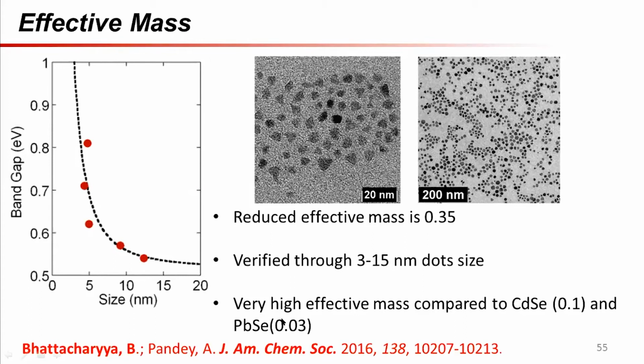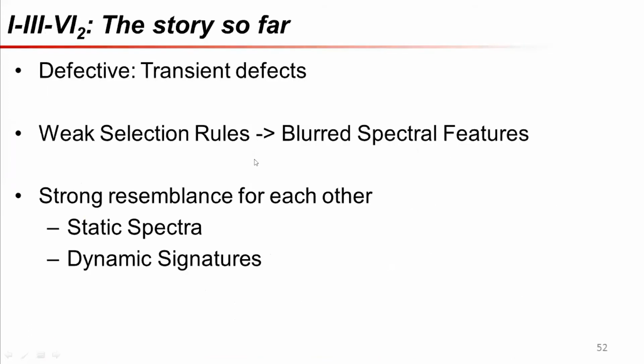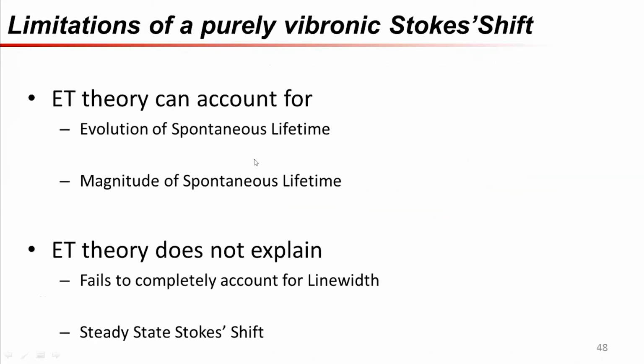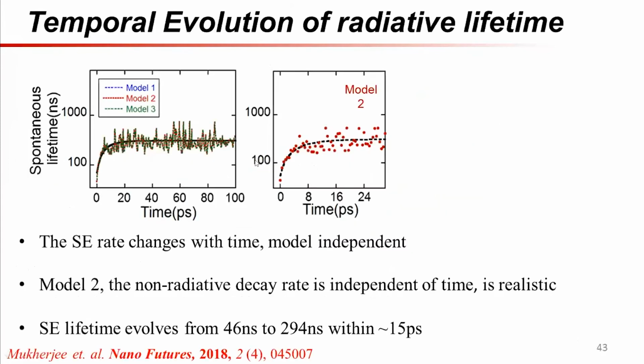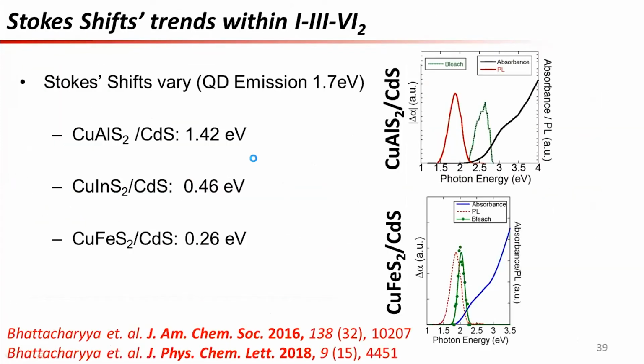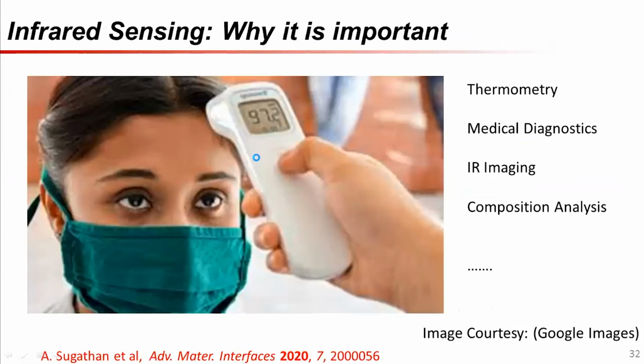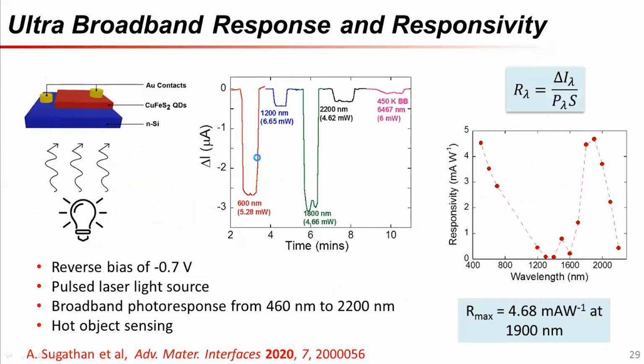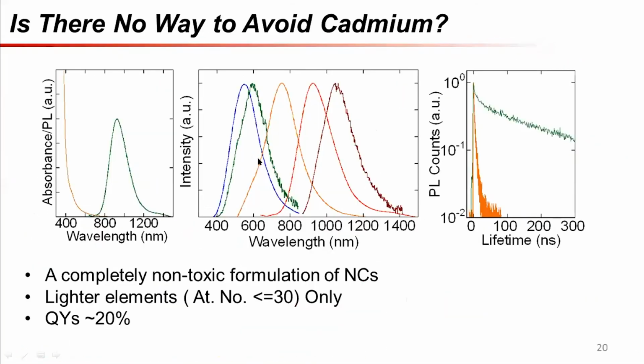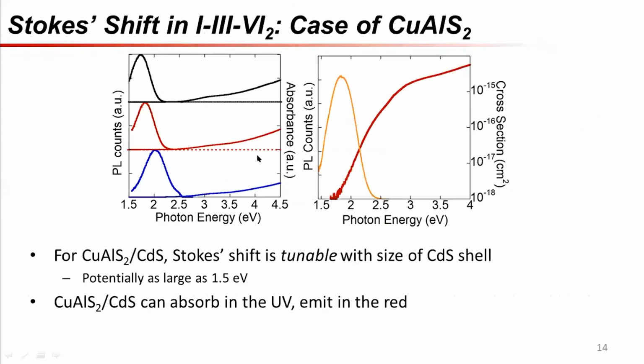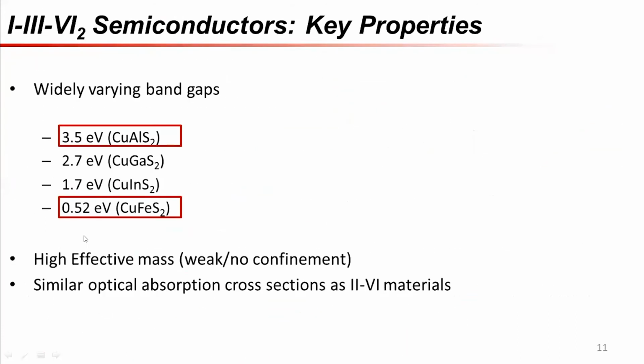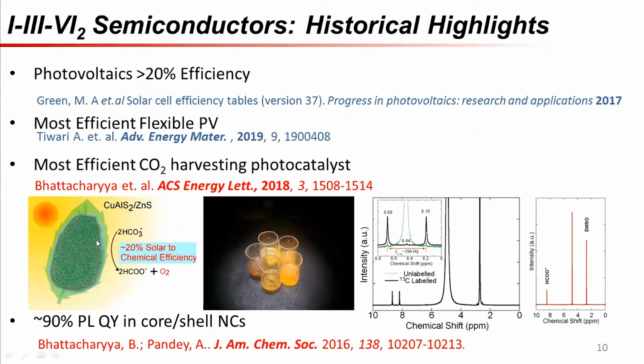Now, there's a question from Dr. S. Manivandan. Is there any charge transfer possible? Absolutely. There is definitely active possibility of having charge transfer in these materials. My favorite example of charge transfer would be coming out of copper aluminum sulfide zinc sulfide. It's a material which we are actually, as I said, very, very excited about. That's because it has really fast, essentially an ultra-fast charge transfer, which occurs to the surface. And this allows this material to have extreme photocatalytic activity.